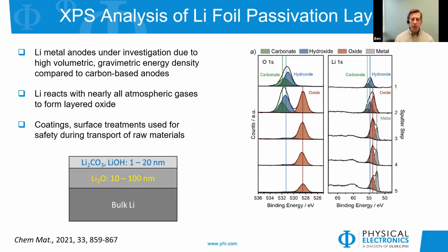And so the general idea is that if you have a bulk lithium, you probably have a lithium 2 oxide on top, and then a lithium carbonate, lithium hydroxide. And with XPS, we can look at those different binding states of the lithium material to understand the relative intensity of those states. As shown on the left, we're looking at an oxygen 1s peak for a lithium passivated foil that has basically not been sputtered, so it's somewhat as received.